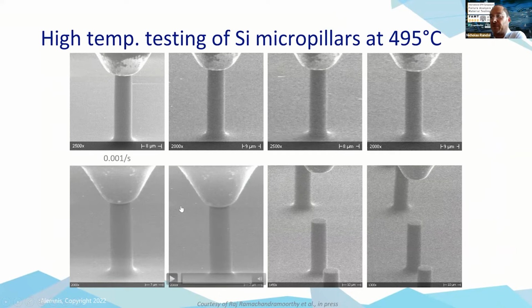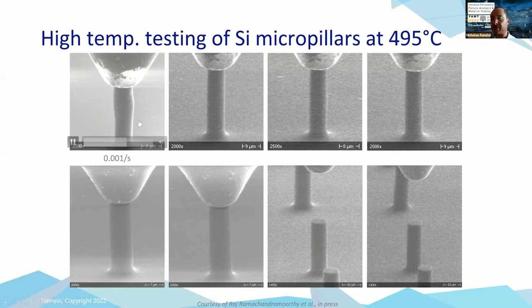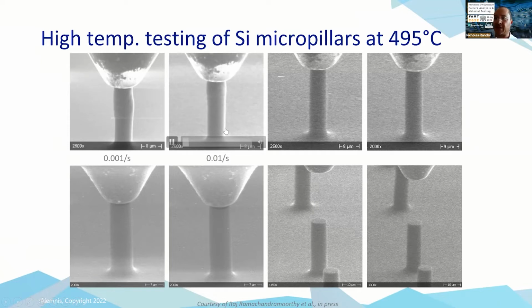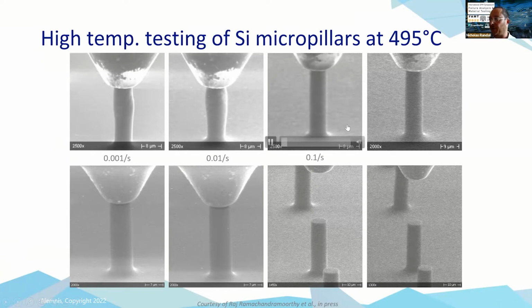Now, we assume that silicon is a very brittle material, but when we deform it at high temperature, we see it's actually pretty soft and ductile. You can see it's a very slow test, 0.001 per second. These are all done with different strain rate jumps. So here we're still testing because it's a very slow test. Let's go to the next one, 0.01. So you can see here, ductile deformation of the silicon pillar. You can see necking occurring, but we don't actually fail the silicon. We just deform it in a ductile way. So let's let that one run, go to the next one.